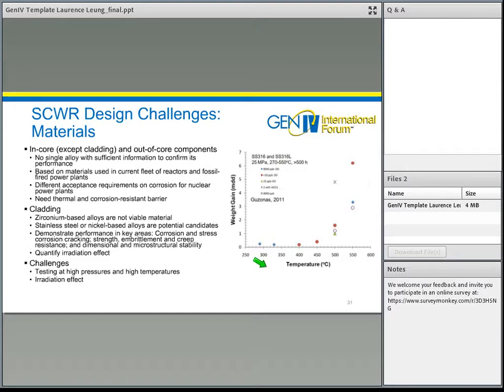So one of the key areas that we find challenging is the cladding. Because of the high temperature operating condition, the zirconium-based alloy currently used in reactors is considered not a viable material. So the majority of the fuel concepts adopt stainless steel or nickel-based alloy as their candidate. To qualify those materials for use in the SCWR, we have to demonstrate the performance in key areas, for example corrosion and stress corrosion cracking, strength, embrittlement or creep resistance, and the change in dimension and microstructure during the operation duration.